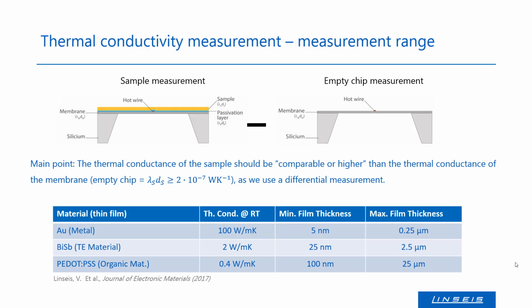If the influence of the sample layer on the thermal conductance is too small, the measurement accuracy will be bad. Nevertheless, as we use an only 100 nanometer thin silicon nitride membrane in combination with a powerful lock-in amplifier, this gives us a very broad measurement range, as can be seen in the table.